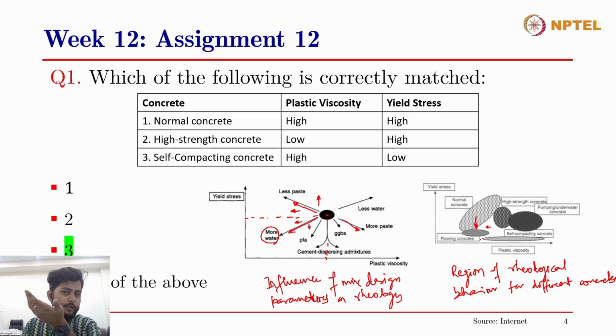So in case of a flowing concrete, as I mentioned, the pumping effort that you require in the case of a roller compacted concrete or a flowable concrete, a pumpable concrete, is not much different. So the viscosity is not very different, but the yield stress has decreased so much that in the case of a roller compacted concrete, you're getting a zero slump, while in the case of a pumpable concrete, you're getting, let's say, 150 slump or so.